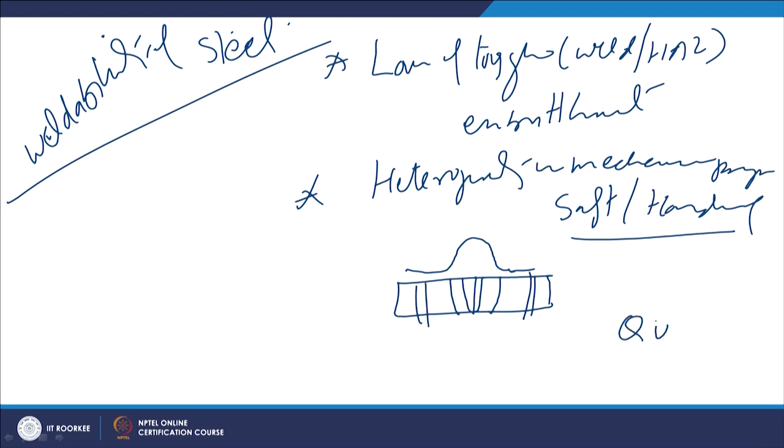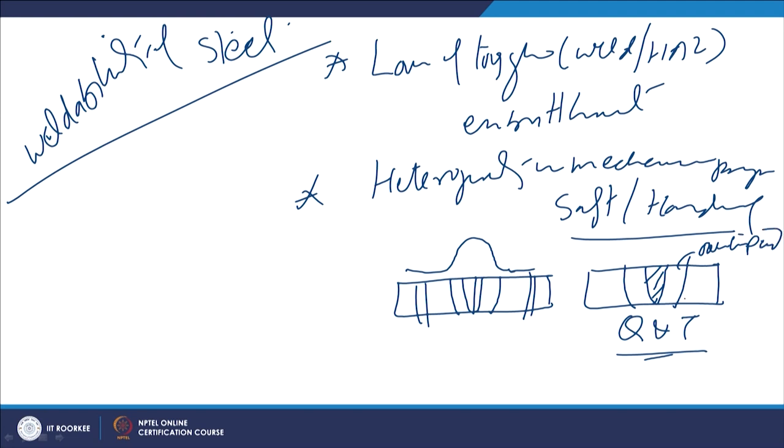But if the steel is in the QT condition, then we will notice that due to the higher cooling rate during the welding, the weld zone invariably experiences the martensitic transformation and so the higher hardness, but the zone next to the weld metal is over tempered, and that is why this zone experiences the loss of hardness. So, the base metal is having higher hardness, but as we approach the heat affected zone, hardness is reduced. Then in the weld metal again hardness is increased, then hardness is reduced. So, the reduction in hardness adjacent to the weld metal, which is the heat affected zone, this loss of hardness